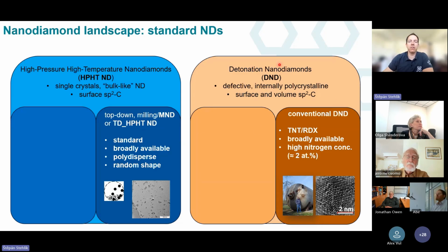On the other hand, we have the detonation nanodiamonds, which are very defective particles. I call them internally polycrystalline, because nearly every particle is like a twin, or you can see some defects. And the sp2 carbon is not limited only to the surface, but can be found also along these grain boundaries and in some regions inside the particles. In addition, they contain 2% nitrogen, which, as you will see, is very important and so far not appreciated that much.